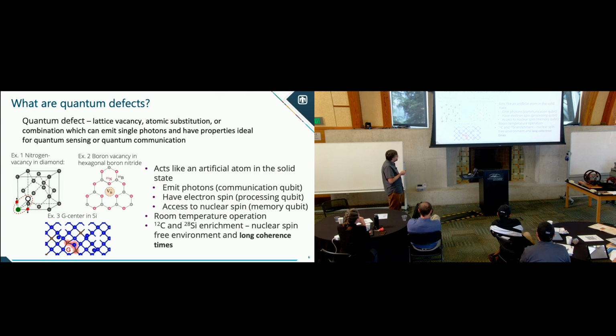Now, in some cases, particularly with hBN and diamond, you can operate at room temperature. That's not true for all defects. Nitrogen vacancy and boron vacancy are ones that do operate at room temperature. Others, like the G center in silicon, well, silicon is a narrower band gap material, so thermal excitation requires you to get down to 4 Kelvin. But the nice thing about particularly silicon and diamond is carbon-12 and silicon-28 enrichment. So you can make nuclear spin-free environments and get really long coherence times. One of the detriments of hBN is that you can't do that. Boron and nitrogen don't have spin-free isotopes, but we're learning to deal with that anyway.